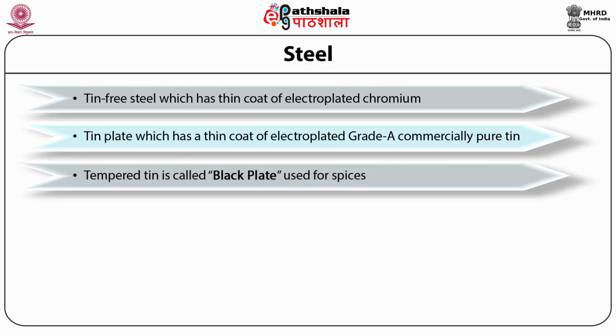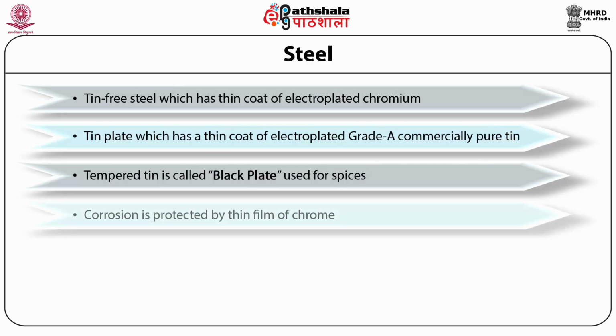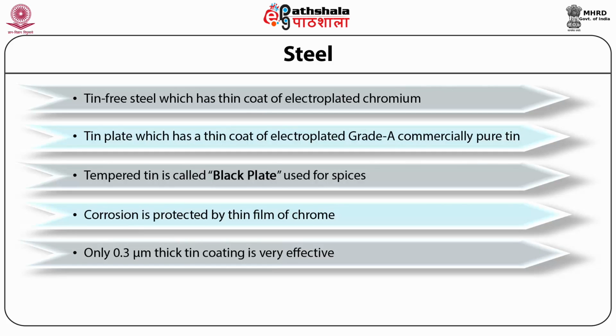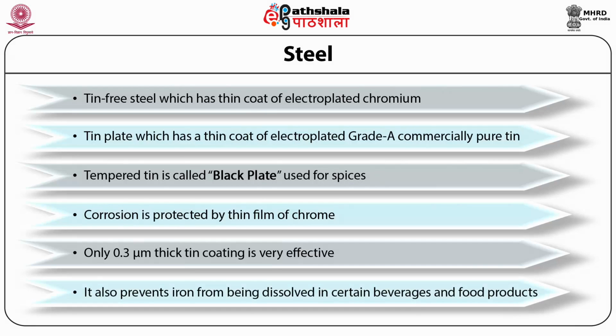An electrochemical passivation treatment, usually with sodium dichromate, stabilizes the surface and adds a thin film of metallic chrome or chromium to enhance the corrosion protection. Although the tin coating is only about 0.3 micrometer, it resists corrosion not only by the protective layer of tin on its surface but also as a cathodic reaction that minimizes oxidation at any pinholes or bare spots which may be found in steel plates. Tin coating also prevents the iron from being dissolved in certain beverages and food products, mainly acidic types of products.